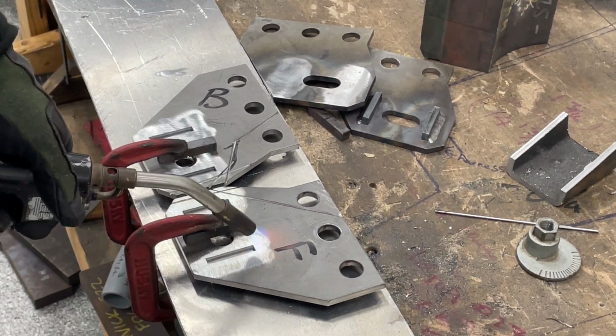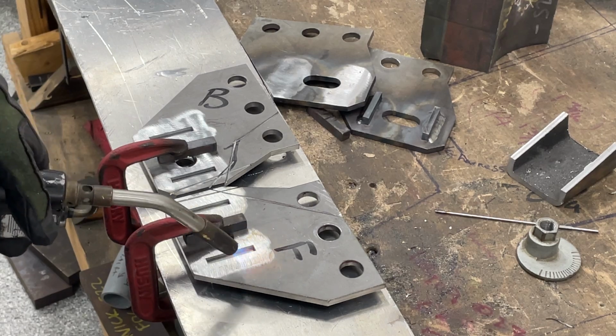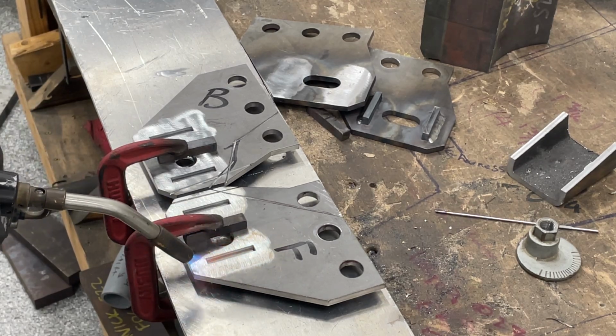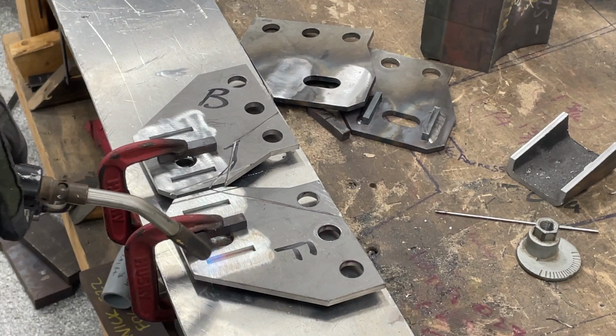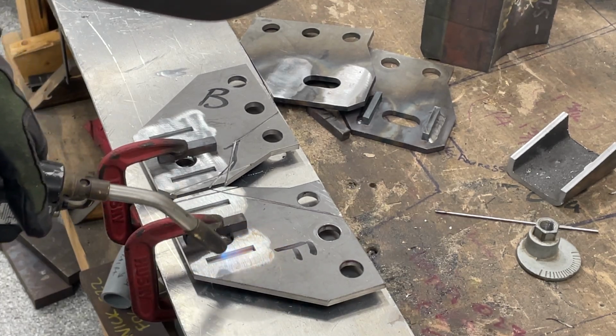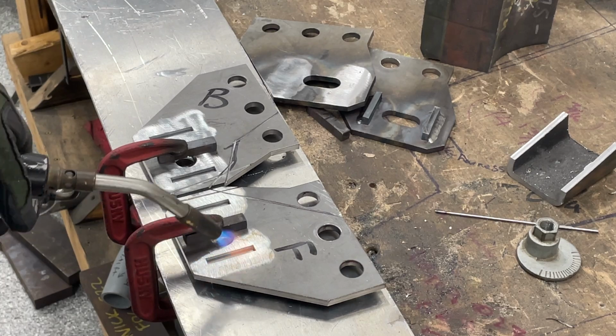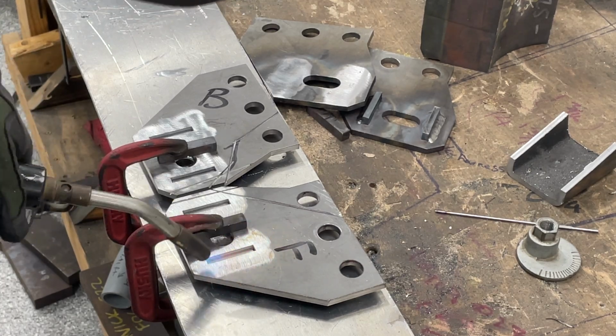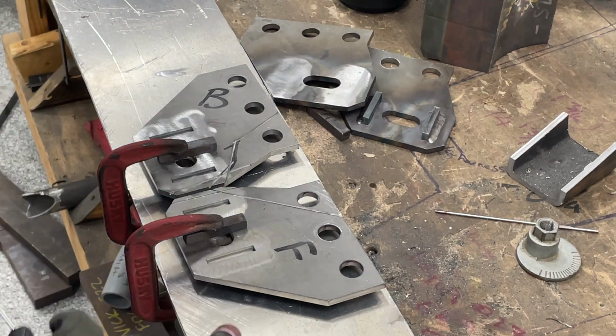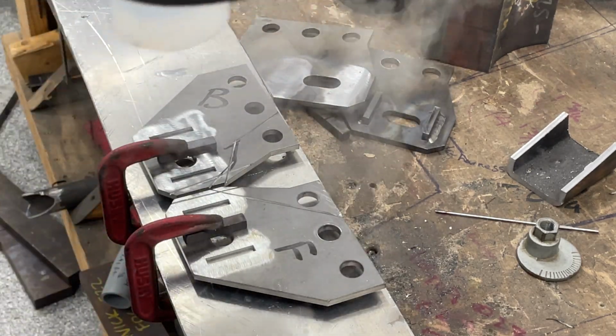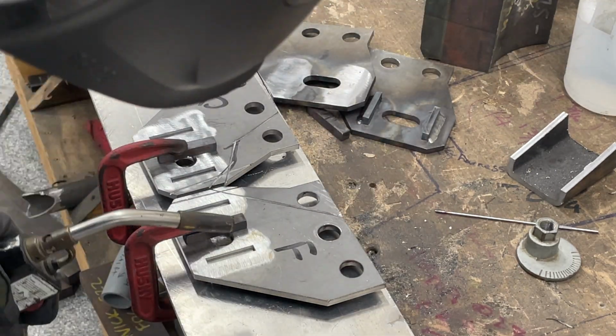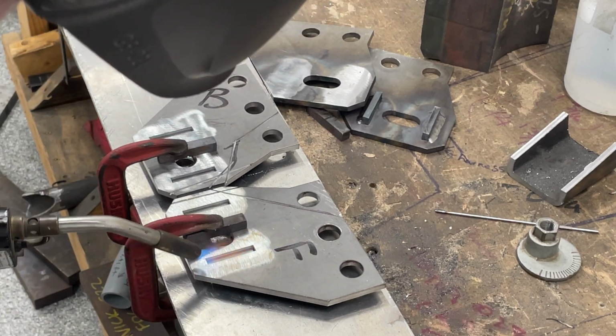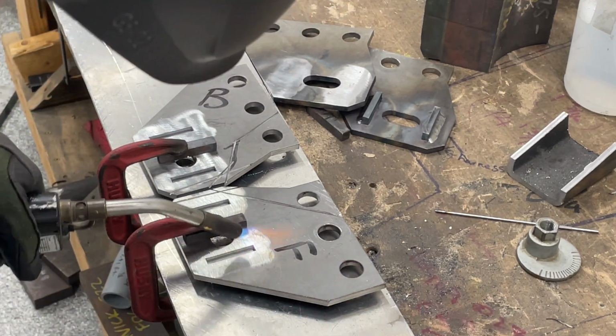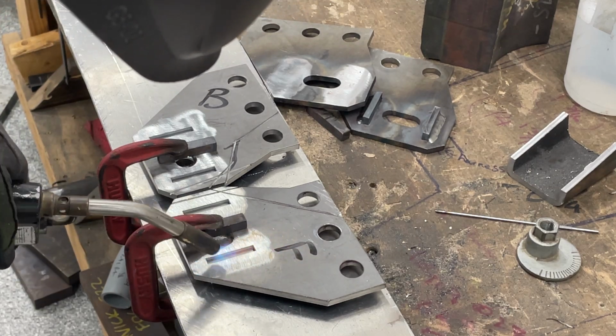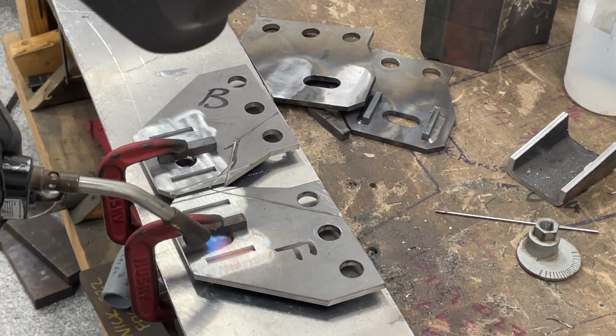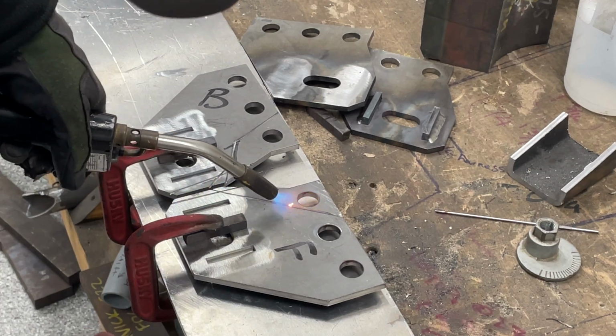In a shop, you would have stuff like thermocouples, temperature probes, or special wax crayons that melt at certain temperatures. We call them temple sticks. Whenever you're welding alone in a shop like this, if you can preheat the part and then zap it with water, if the water flash evaporates, you know it's over 200 degrees Fahrenheit, which is good in our case. Just make that water disappear, make it evaporate away. We're going to focus on this area here first before we weld something else. Ooh, that's fun. All right.